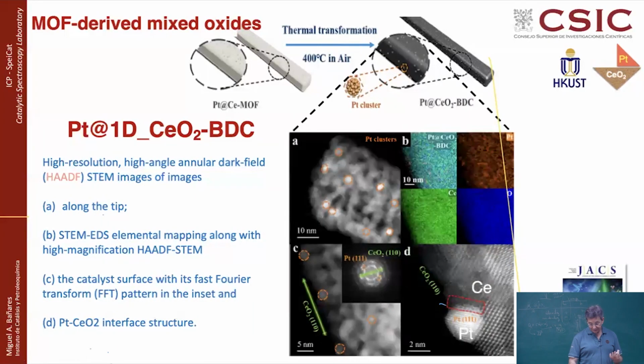And actually, when you characterize, you will see these ceria nanorods, and these bright dots correspond to the platinum nanoparticles. And you can even look at how there is an interface between the platinum nanoparticle, about 2-3 nanometers, and the ceria nanorods. And you can see these locations and changes just at the interface between the platinum and the cerium. And that will typically generate defects or reactive sites. And you have a very big dispersion of exposure and interaction between the platinum and the cerium.